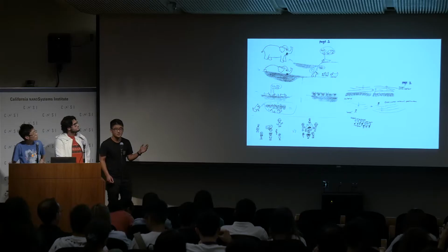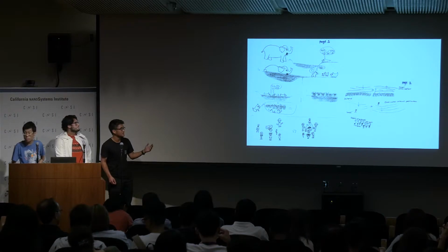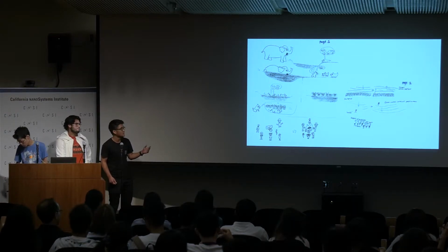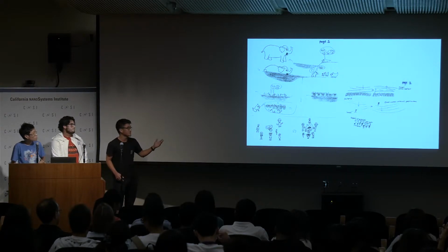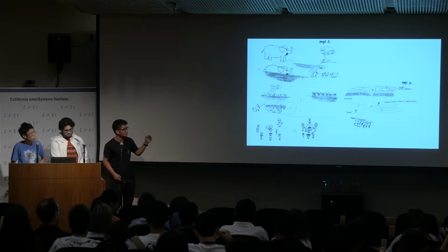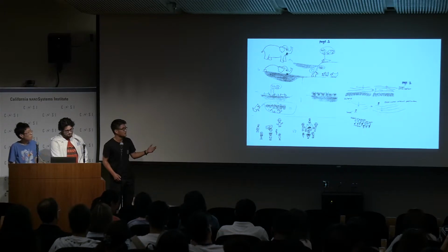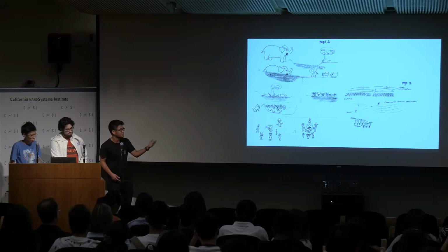So we were able to find the radius of that monolayer, and knowing the volume of the monolayer, we were able to calculate the height. And because the monolayer is a single molecule thick, that height was the size of a single molecule of oleic acid. So in this picture, this is just an example of indirect measurement. Because of the proportion of 6 dogs to 1 elephant, they were able to calculate the volume, or the number of dogs that would fit in the water.